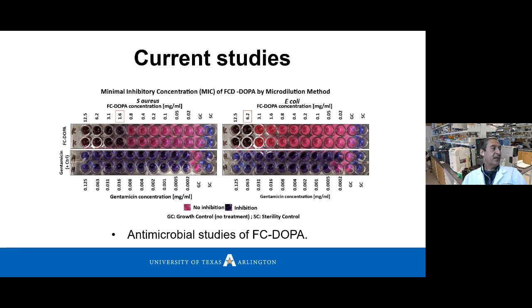We also tested our material on antimicrobial properties, and we found that our hydrogel made of fucoidan and dopamine can kill S. aureus and E. coli. We determined the minimum inhibitory concentration of these materials. And in the next slide, we're going to see, can you please go to the next slide, Dr. Nguyen?